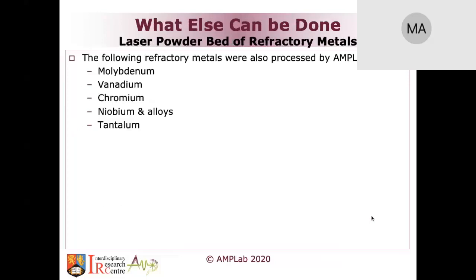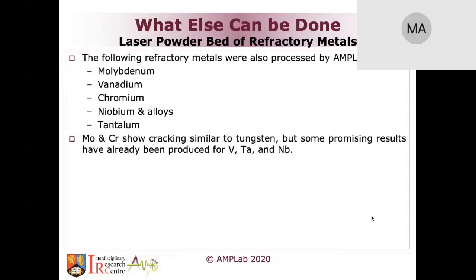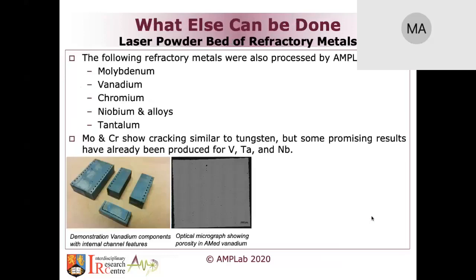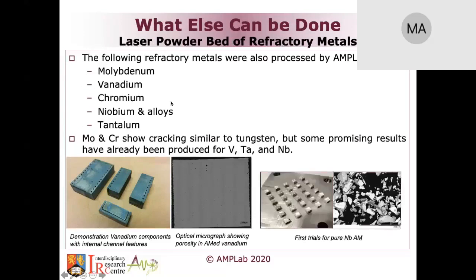So what else can be done? Well, refractory metals in general, we can print many of them, and we've done previous work printing, for instance, vanadium. This is a vanadium alloy, which we know you can print confidently. It prints really nicely, in fact. We have printed chromium with poor success, no success actually, with chromium and molybdenum. Both showed massive cracking. We printed more recently niobium, and niobium seems to print quite nicely, even if you start from faceted powder like that one.